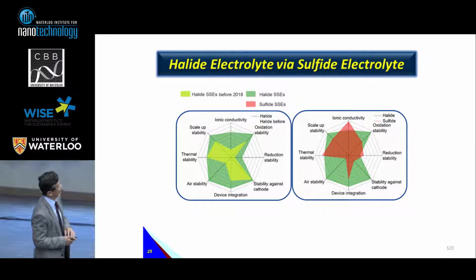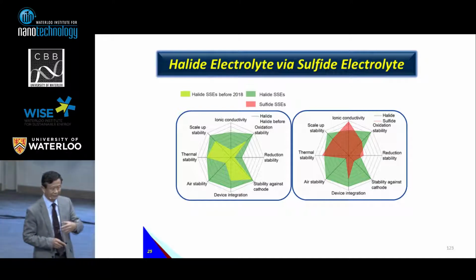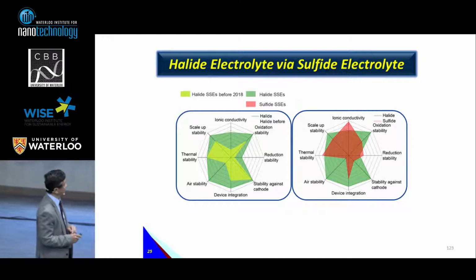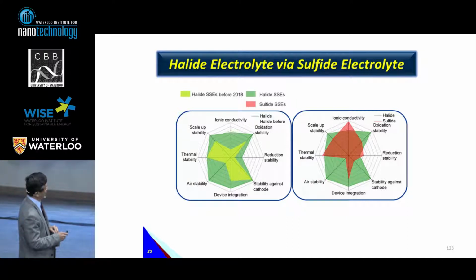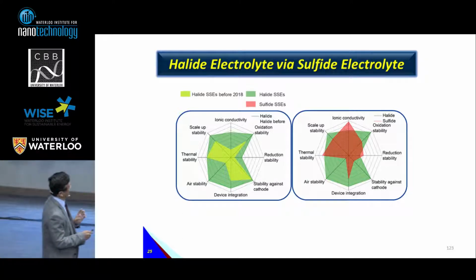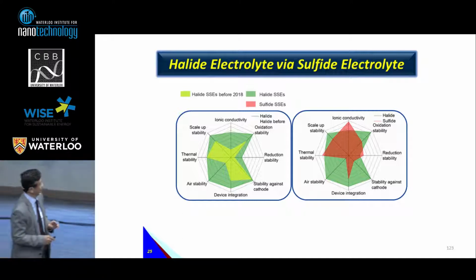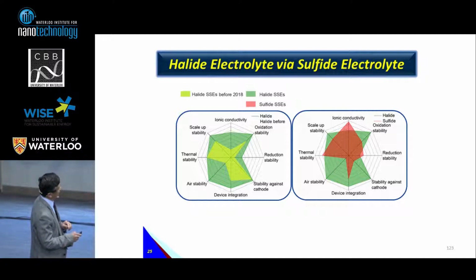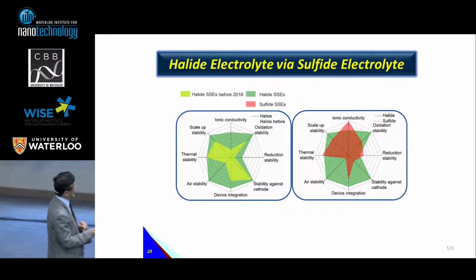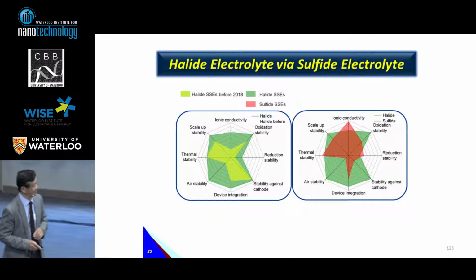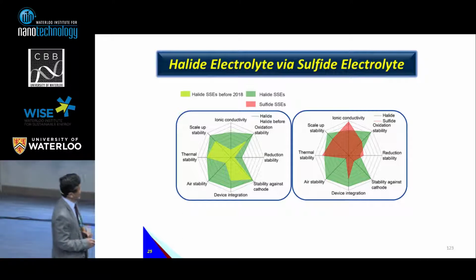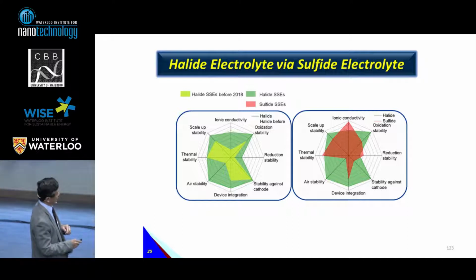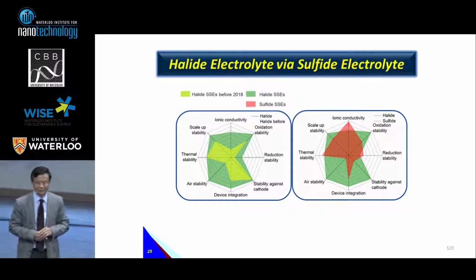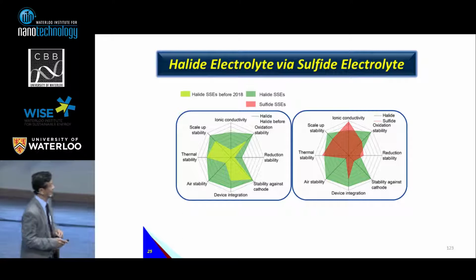So talk about this halide-based solid-state electrolyte, and then compare with the promising one, sulfide. You can see many different properties. Before last year, the yellow one, this type of electrolyte had very poor performance in many things. But this year, the green one suddenly improved a lot. But still, you see the one challenge is with the anode. So other properties, ionic conductivity and the cathode, air stability, all addressed. And if you compare with sulfide-based electrolyte, you can see the green one is much better than the red one. So that means this type is very promising for solid-state batteries.